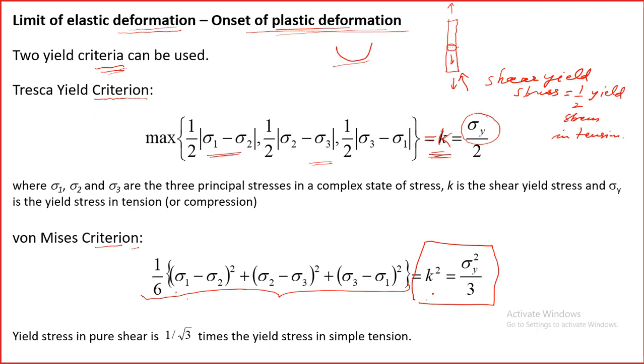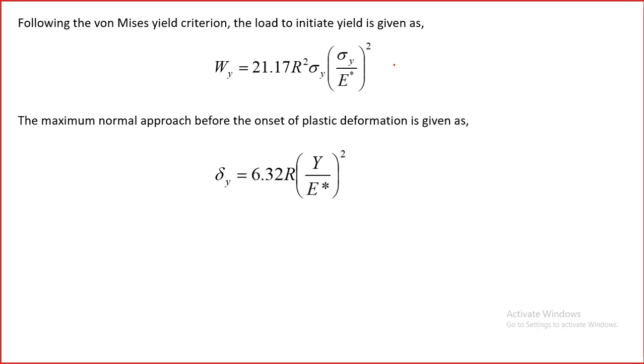If we compare Tresca with von Mises, von Mises is approximately 15% larger than the Tresca yield strength. Depending upon the situation, people either use the Tresca yield criterion or the von Mises yield criterion, and this just tells us at what point the plastic yielding will initiate. For the axisymmetric contact of two spheres, the maximum shear occurs beneath the surface on the axis of symmetry, the z-axis, and it is given by this one.